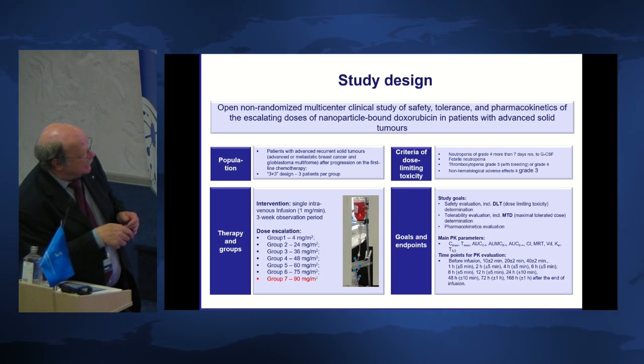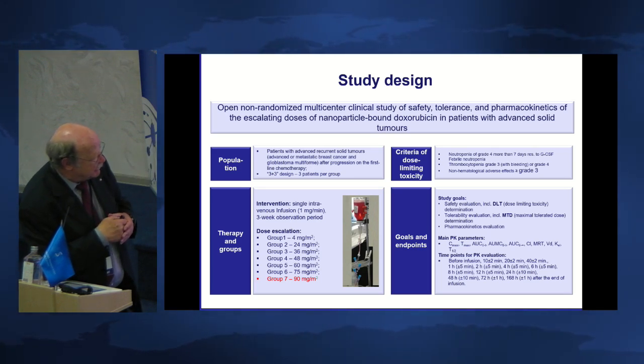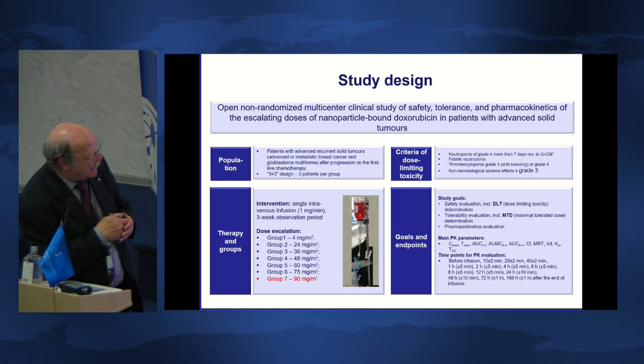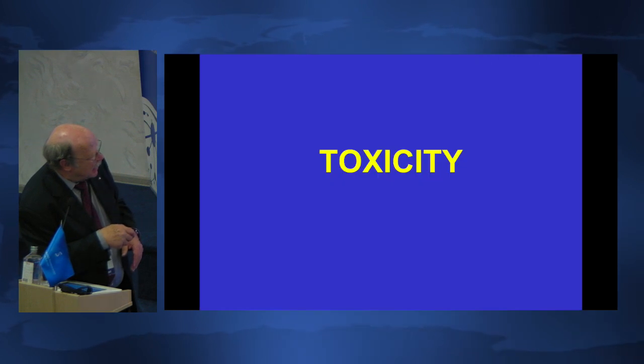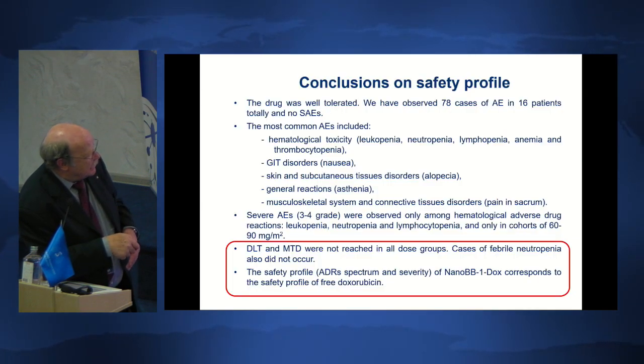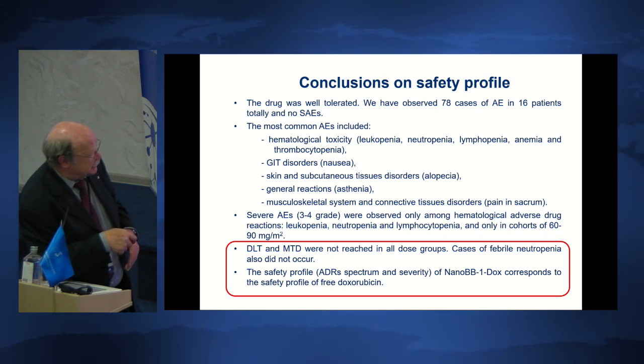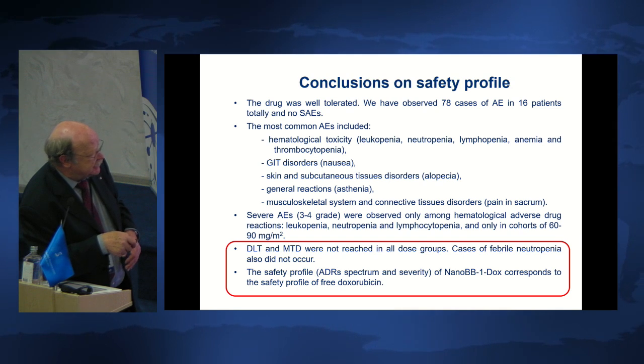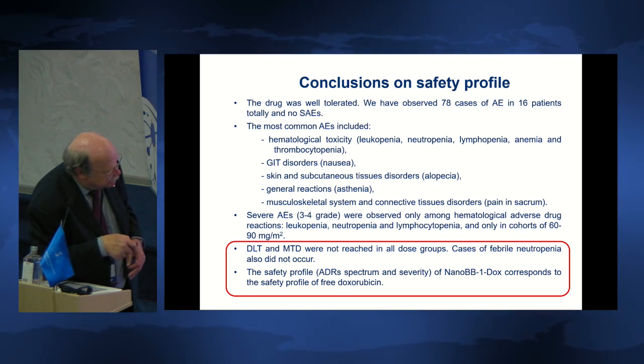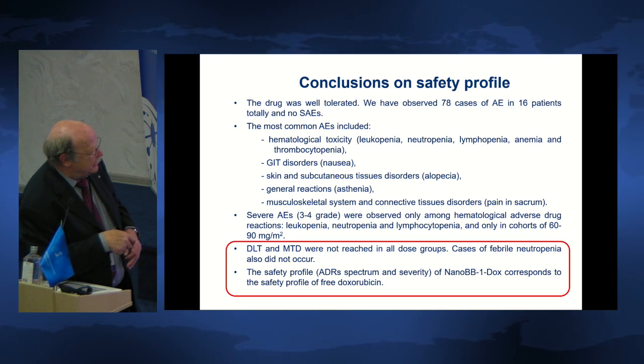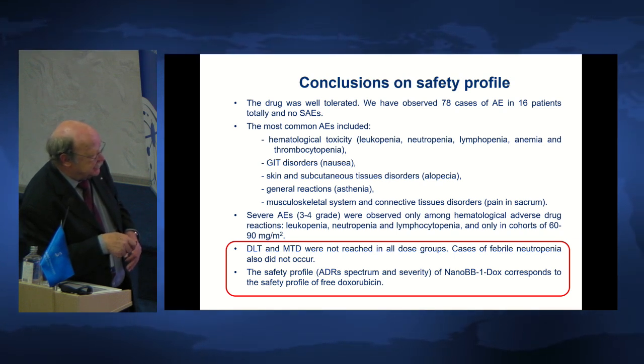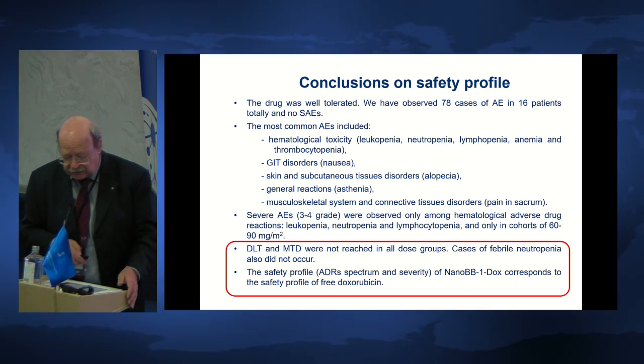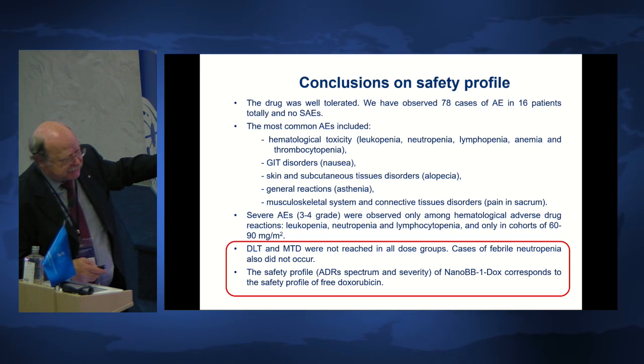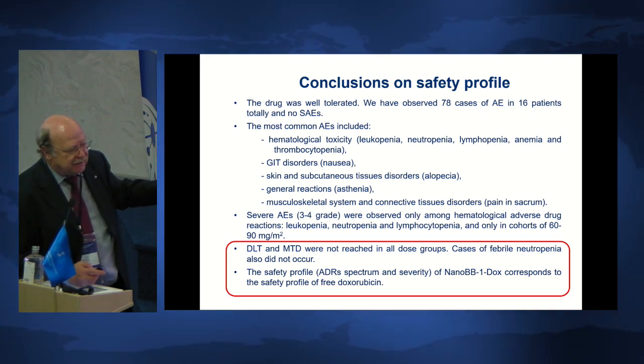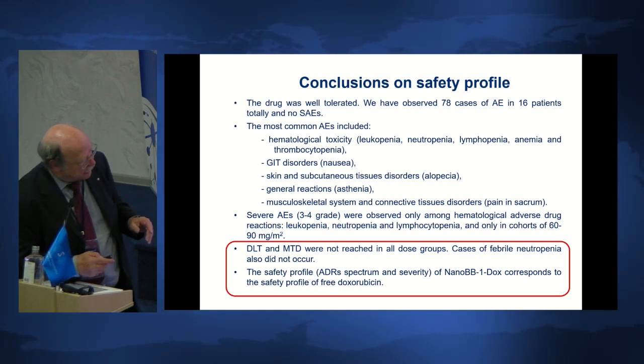And this is the study design. We went up to group 7 with 90 milligrams per square meter of doxorubicin. And you see here the parameters. And the outcome: the dose-limiting toxicity and the maximum tolerated dose were not reached in all those groups. Cases of febrile neutropenia also did not occur. The safety profile of this formulation corresponds to the safety profile of free doxorubicin. So there was no increase in toxicity. There was even a slight, but not significant, indication for a decrease of toxicity.